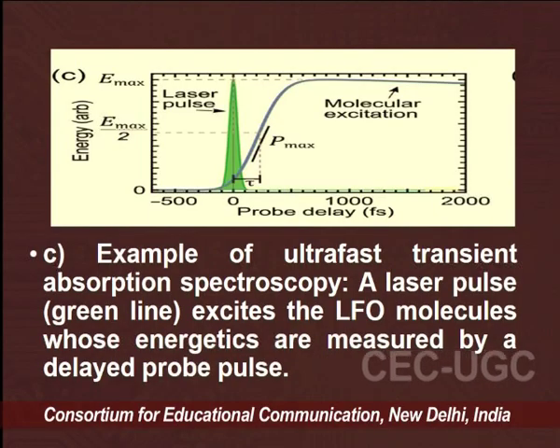So, here we are using the ultrashort pump pulse, and the energy stored in the sample corresponds to the number of excited dye molecules, and it is measured by the transmission change of a second ultrashort probe pulse whose temporal delay with respect to the pump, that is tau, is controlled by the mechanical delay line. You can see here an example of ultrafast transient absorption spectroscopy, where a laser pulse, defined by the green, excites the LFO molecules whose energetics are measured by the delayed probe pulse.